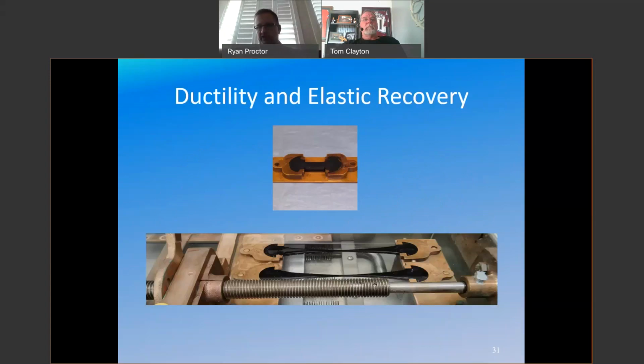This is one of the tests that you'll see in Colorado. I'm really going to talk about two tests here. They're similar in some sense. You look at that mold in the top. That's where you put asphalt into a dumbbell shape. Different specs have different sizes, but they're all somewhat similar. And then they go into a ductility bath. Generally speaking, those ductility baths are either at room temperature or at 4 degrees Celsius. And for a ductility, they pull these out slowly until they break. And when those break, that's the value that you get.